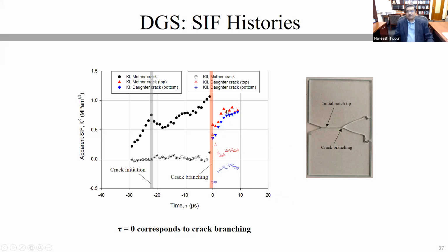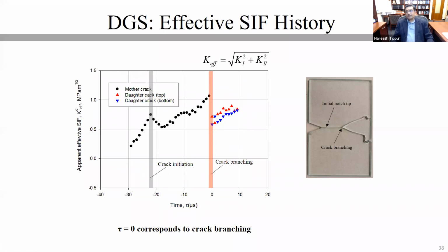Also, I want to point out that the values of K1 never increased to a high value of around 1.1, 1.2 megapascal root meter. I'm throwing a bunch of numbers here because these are the ones that make sense in terms of the consistency and the precursors that I'm going to talk about down the line. The effective stress intensity factors were created by using both the mode 1 and mode 2 stress intensity factors. These trends look very similar to that of K1 because that is the dominant contributor in this particular geometry and in this particular experiment.